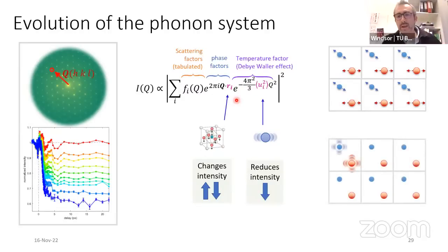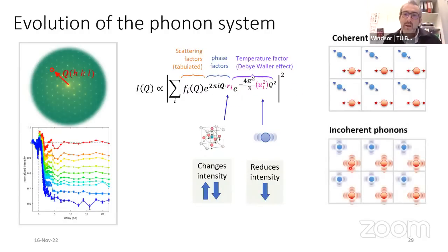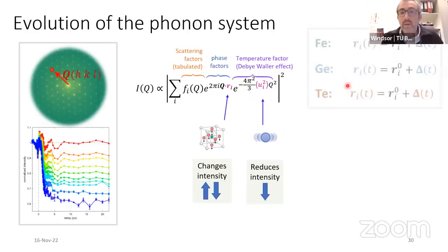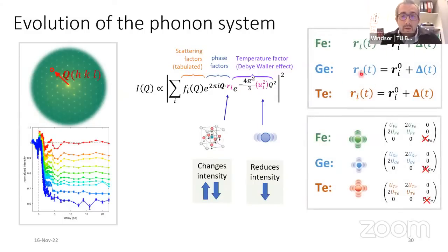And so this kind of looks like this. We just have a growth in how much all of these atoms vibrate. Now this is nice, but also can be described analytically as well. So if we model these coherent phonons, if we know the phonon distribution of this material, and we typically do, we can describe the coherent phonon using a term that is time dependent. It would be a sinusoidal term, and it would be different for every single ion species. So for iron i, for germanium i, for tellurium i.